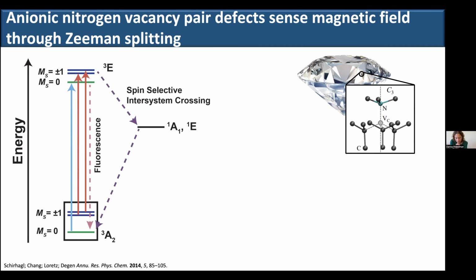One way that you can measure that is with a magnetometer, but that's very technically difficult because you have this diamond anvil cell with all of these components that aren't fully compatible with a magnetometer, especially if you want to laser heat your sample. So another way that you can imagine doing this is using a built-in magnetometer. We've been synthesizing these compounds in diamond anvil cells.